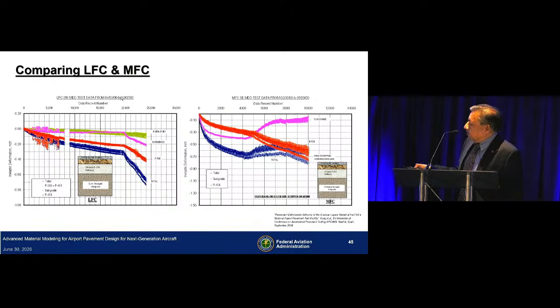And the results that I've shown here are permanent deformation as measured by multiple depth deflectometers for the different component layers of the pavement structure. On the low strength subgrade, what you see is the subgrade deflections are very low. It's the sub-base material that is accumulating permanent deformation. And this is the location at around 20,000 passes where we increase the wheel load from 45,000 pounds per wheel to 65,000 pounds per wheel, and that's when these deformations start increasing.